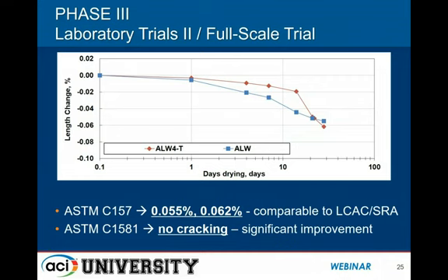But it wasn't until we get to this figure when we started to incorporate another strategy, which was using lightweight aggregates. And these are pre-wetted, or some say saturated, although they don't really fully saturate. These lightweight aggregates, and these are lightweight fines that are being utilized, are materials that are becoming very popular. There's some momentum throughout the industry with regards to using these materials for internal curing, even in Portland-based concrete. In this instance, I believe this was the first attempt that anyone's made to look at this material in conjunction with calcium aluminate cement.